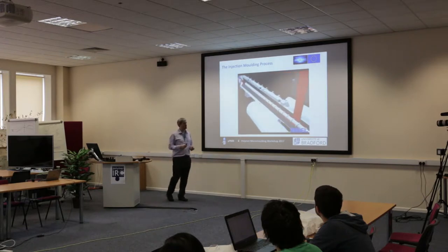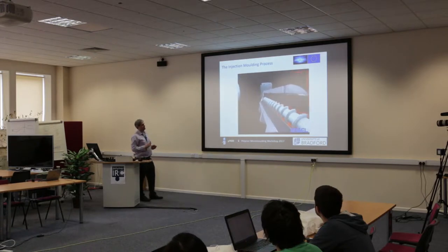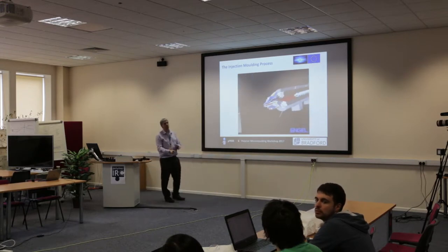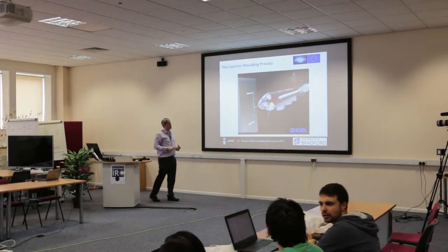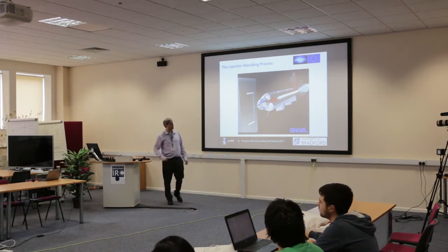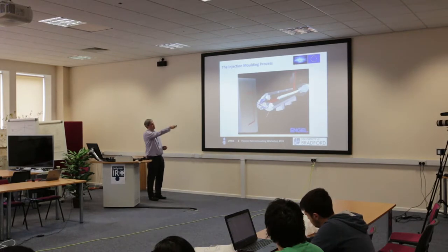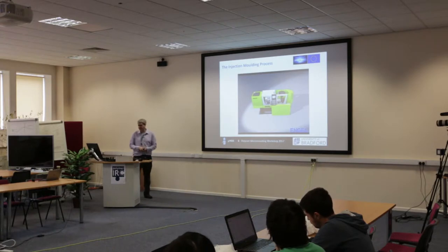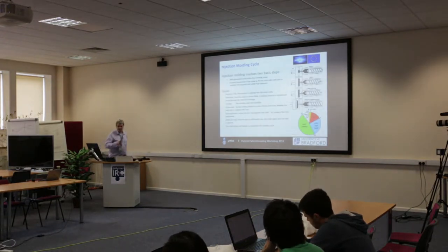The screw geometry is similar to conventional injection molding. This injection side of the machine operates at the melt temperature of the material, which can be anywhere between 200°C and 450°C. The mold side is much lower — typically mold temperatures range between about 40°C and maybe up to 200°C for some high-temperature polymers. The material is cooling and solidifying in this region, which forms our final part.